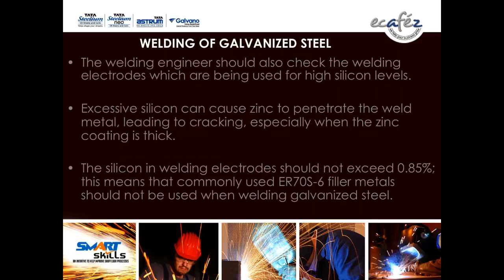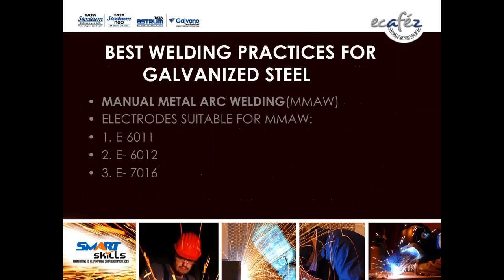The welding engineer should also check the welding electrodes being used for galvanized steel for high silicon levels. Excessive silicon can cause zinc to penetrate the weld metal, leading to cracking, especially when the zinc coating is thick. The silicon in the welding electrodes should not exceed 0.85%. This means that the commonly used ER70S6 filler wire for MIG should not be used when welding galvanized steel.